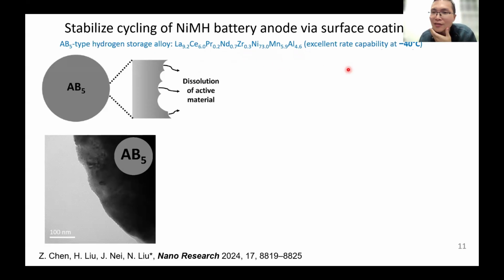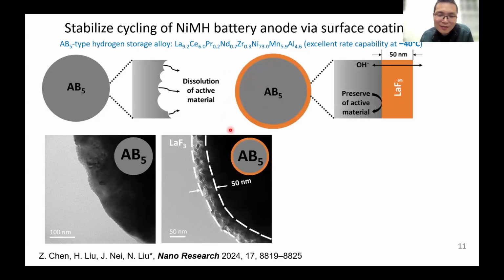So this material is very good at extremely low temperature, -40 degrees C. But it has a dissolution problem. If you cycle it many times, the metal inside will come out of the particle, and that will degrade the performance of the material. So what we did is design and make a coating specifically for this AB5 particle. This coating here is lanthanum fluoride. We chose that because it's stable in the electrolyte, and it has a similar structure and composition: the lanthanum is the same inside the particle and in the coating.